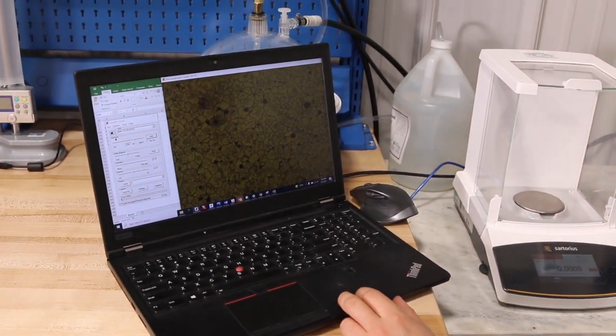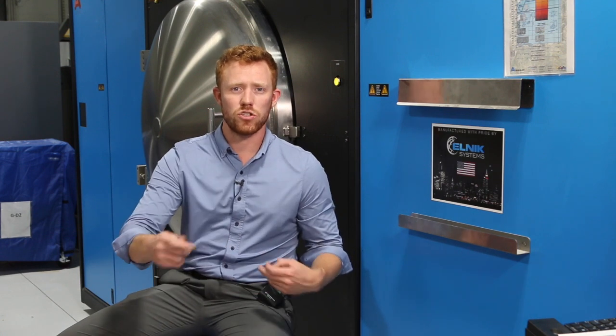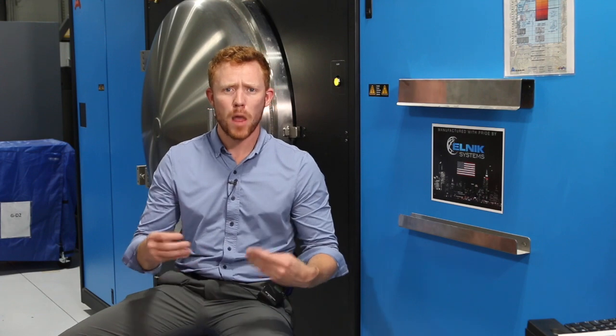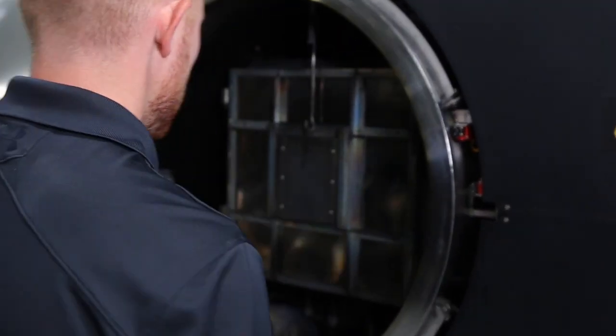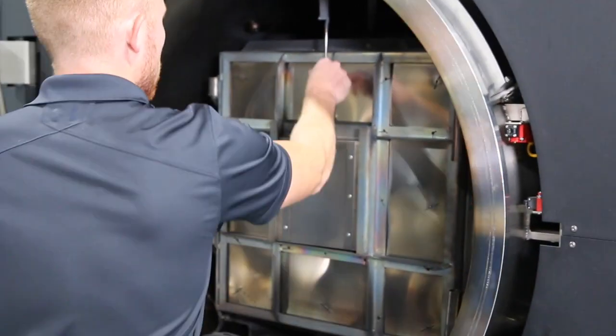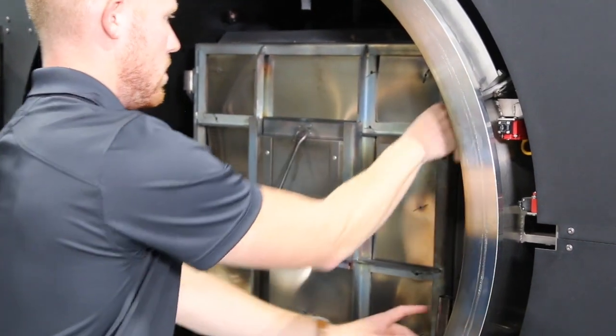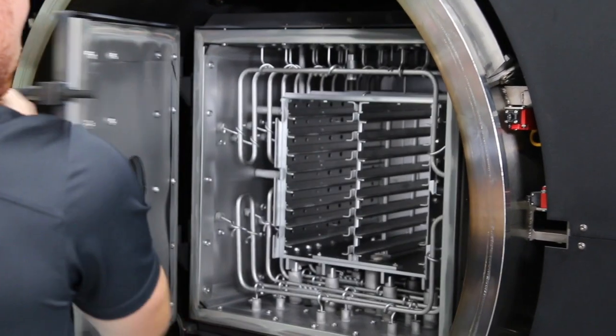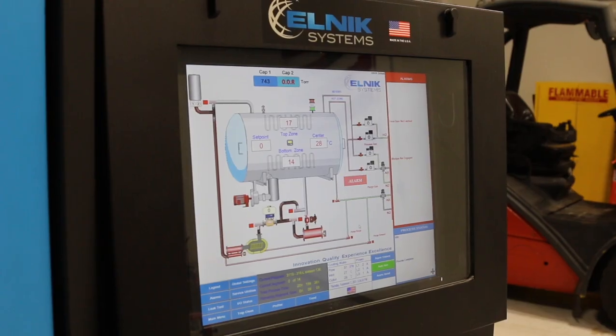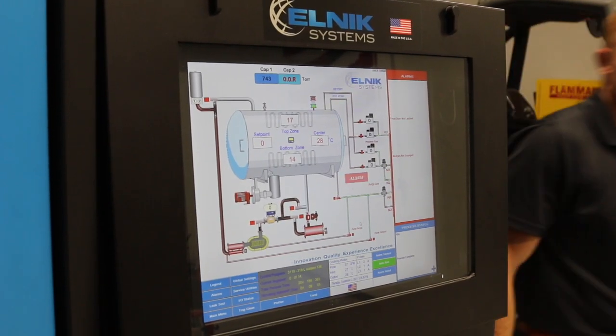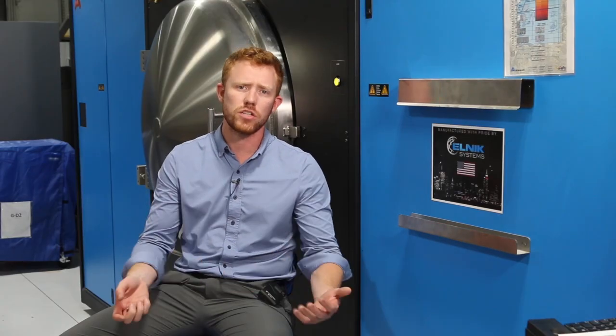To expand on sintering, it's done oftentimes in either a belt furnace, which is a long continuous furnace, or a vacuum furnace, a batch furnace. And that's what we utilize here at Azoth. We utilize a vacuum furnace capable of creating atmospheres in partial vacuum, and nitrogen, argon, and hydrogen, and capable of going up to temperatures around 1400 degrees Celsius, which allow us to create custom cycles to sinter your components.